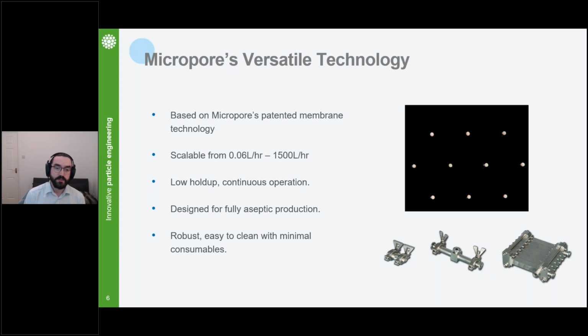This gives us a system that's scalable across the 3 devices that you can see on the bottom of the screen there, from 1 milliliter per minute all the way up to 1500 liters per hour, all using this exact same type of membrane, this exact same type of mixing technology. These devices, all 3, are designed for very low holdup continuous operation, just as comfortable producing a milliliter as they are producing hundreds of liters. All designed for aseptic production, so even if we weren't producing very narrow size distributions, which we are, you could run these fully aseptically.